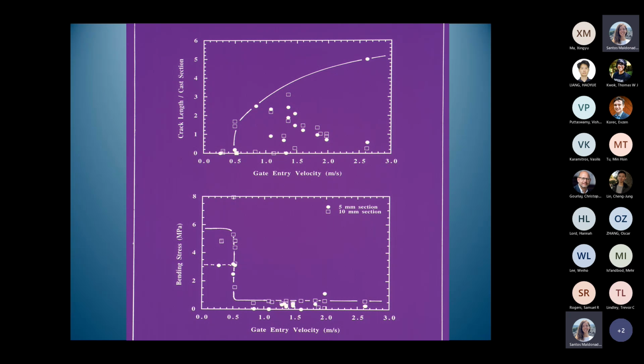So these are his results. These are the crack lengths, and this is the velocity here. So up to 0.5 meters a second, there's no cracks that we could find. And suddenly at 0.5, cracks appear, and then nothing, something, nothing, something terrible, nothing more or less. So here is chaos. And it's interesting to see chaos on plots of graphs. Here you would expect chaos, because this is now being controlled by turbulence. And the turbulence is something that's rather chaotic, and sometimes the metal will jump one way and sometimes it jumps the other, or may not give you a crack. So this is an expected behavior.